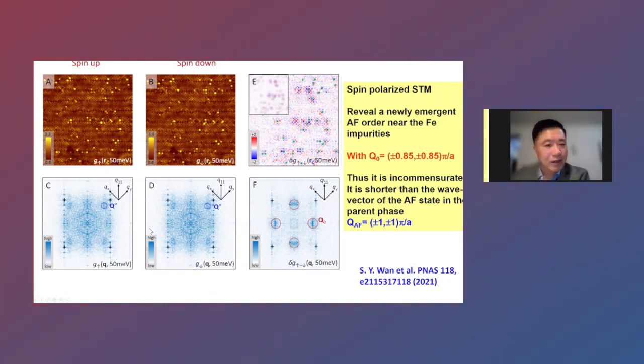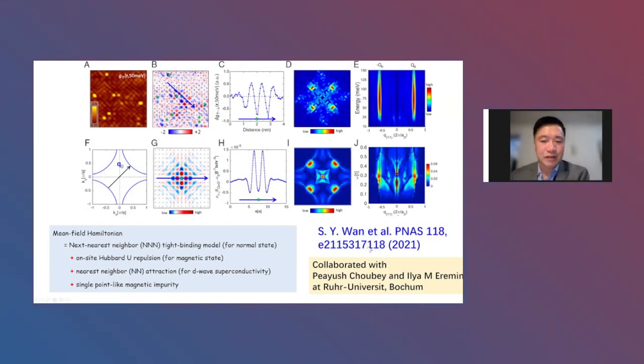So our theoretical collaborator, Professor Ilya Eremin, did the calculation. They assumed an on-site Hubbard U repulsion for the magnetic state, and a nearest neighbor attraction for d-wave superconductivity, and a single point-like magnetic impurity. They did the calculation, which shows this kind of spin polarized contrast pattern, and you can compare it to our experiment. It looks very similar, okay? And also this intensity oscillation, this dispersion also. So it seems that the antiferromagnetism and the superconductivity are very closely interplayed with each other, okay?